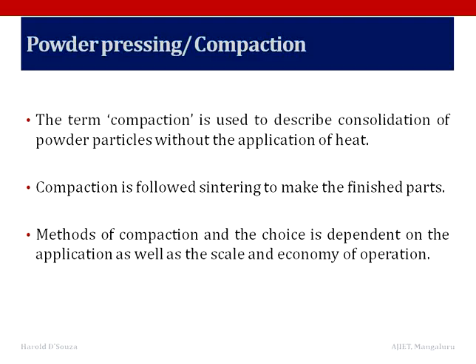In other cases, such as cemented carbides, superior properties can be achieved through hot pressing of the component powders rather than cold pressing followed by sintering. Such high temperature consolidation of powders cannot be strictly defined as compaction, as simultaneous sintering is also involved. There are many methods of compaction, and the choice is dependent on the application as well as the scale and economy of the operation. Most of the methods depend on the application of external pressure on powder contained in a die or a mold. However, some other methods like vibratory compaction and slip casting do not use any external pressure.